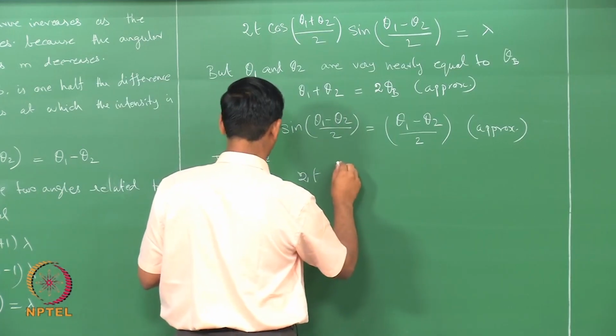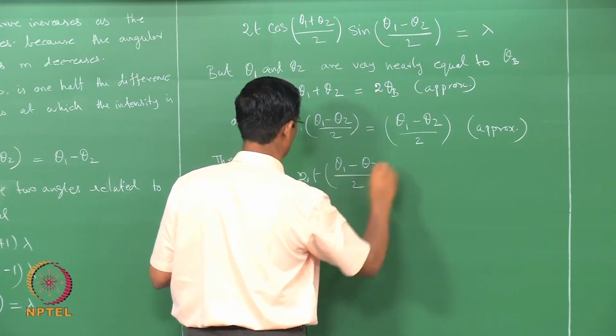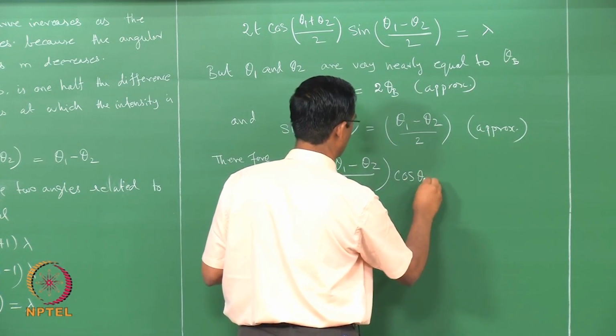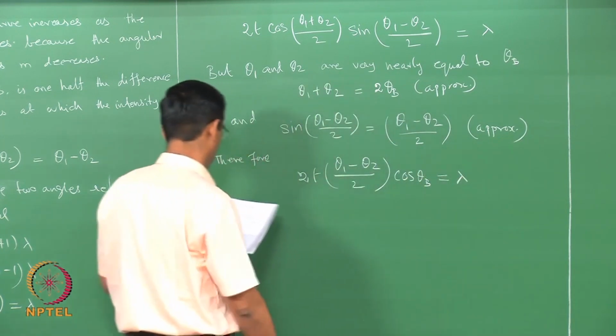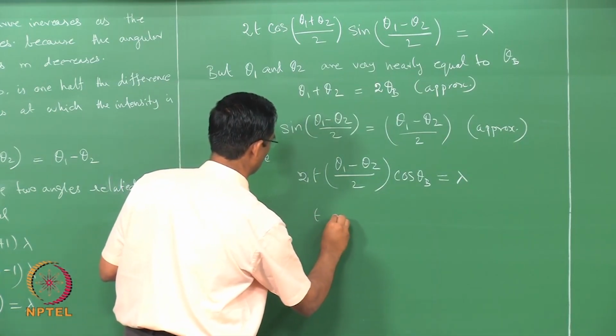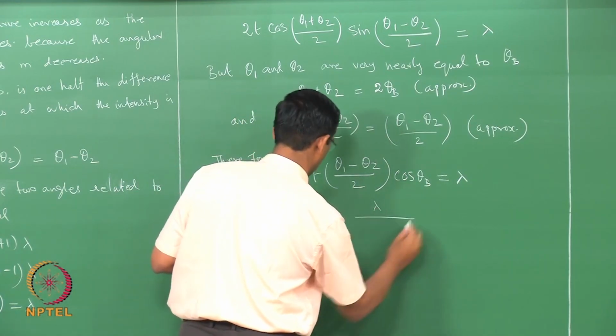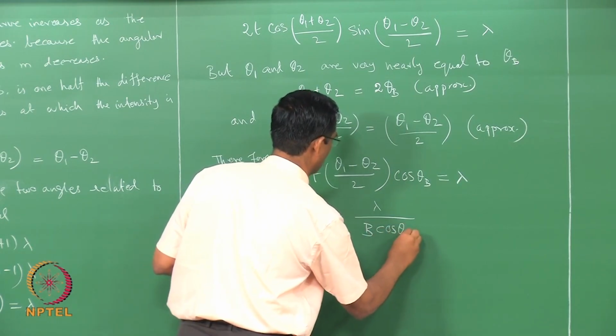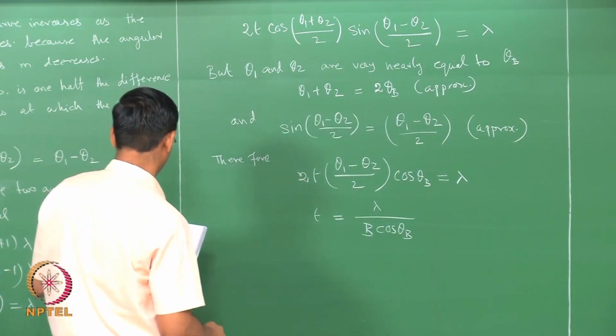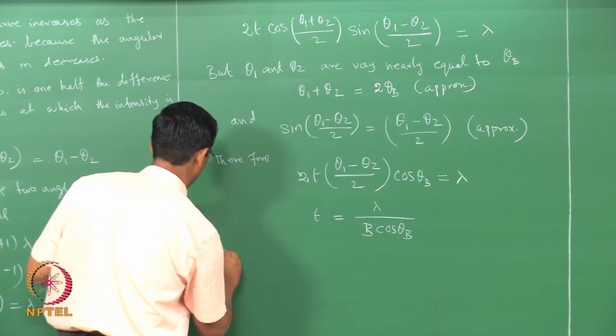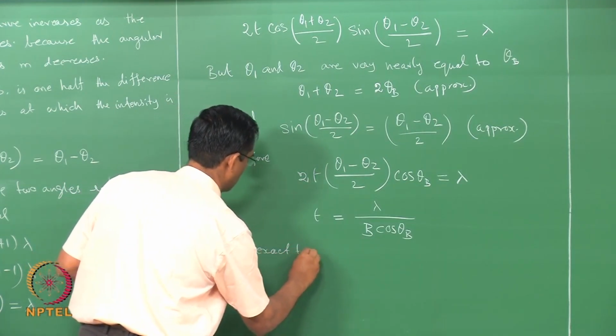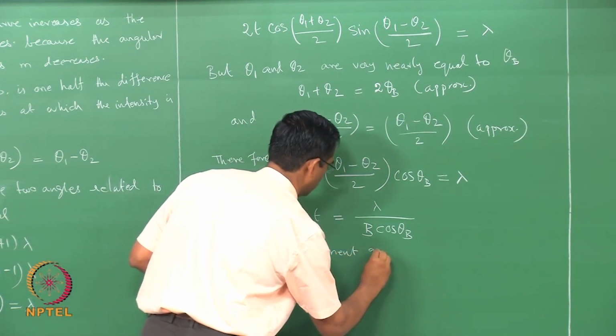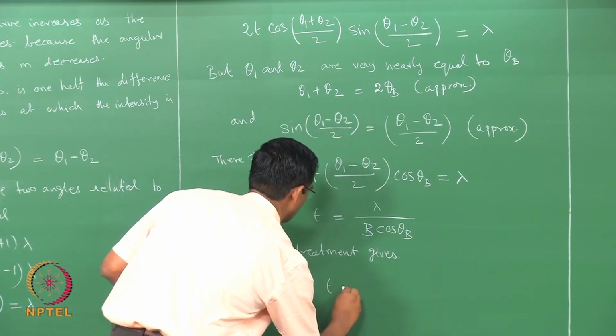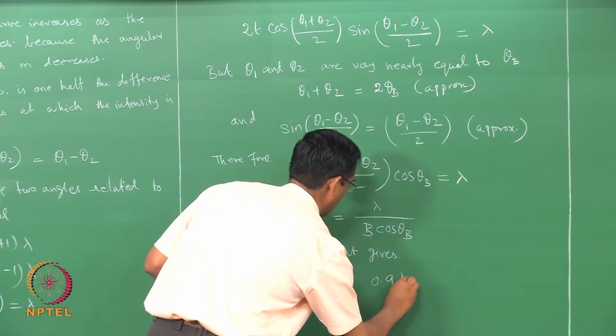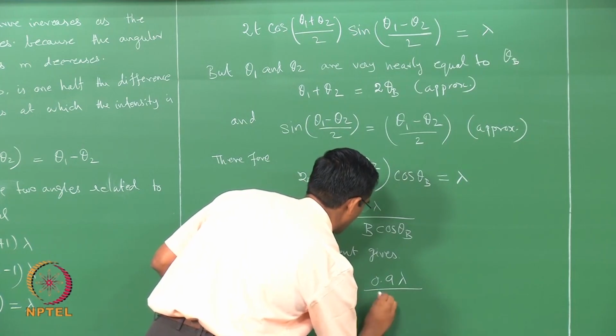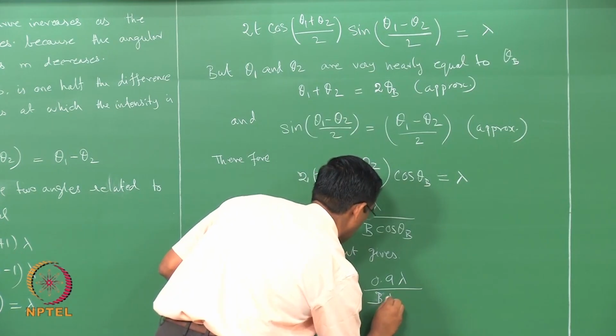So, what you get is 2t times sin of (theta 1 minus theta 2) by 2, times cos theta b is equal to lambda, or t is equal to lambda by B cos theta b, and a more exact treatment gives this as t is equal to 0.9 lambda divided by B cos theta b.